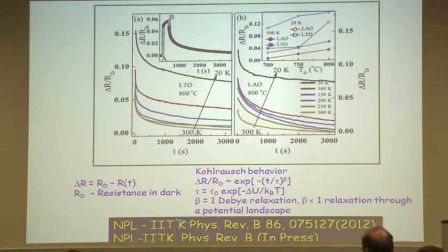And you know when beta is equal to 1, you have the Debye relaxation process with a well-defined activation energy. On the other hand, if you have a potential landscape with several activation energies, then you will get beta less than 1. And this is what we see here. We can extract the activation energy, and the details of all this work are given in these two papers, how the system recovers and what the recovery dynamics is and all that.